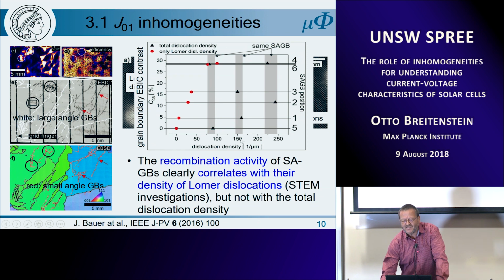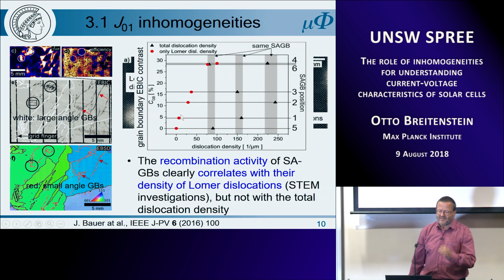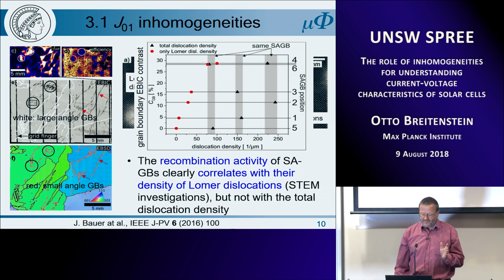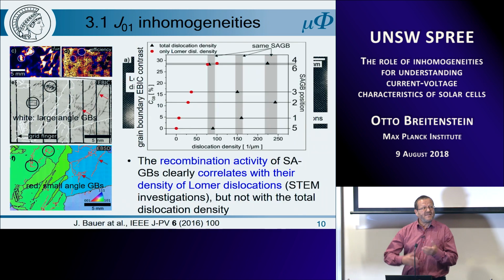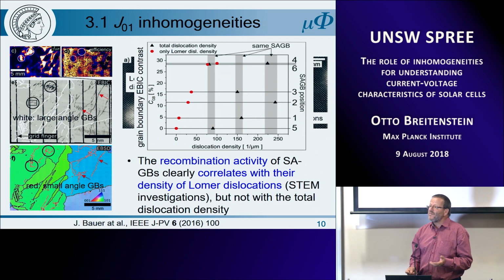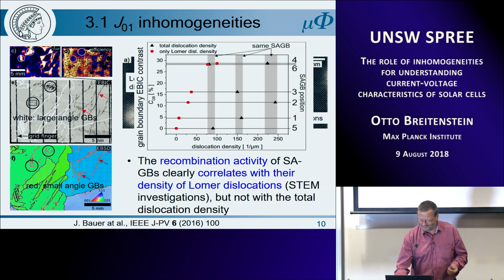total dislocation density. And you see the total dislocation density does not correlate with the contrast, but the Lomer dislocation density does. So we believe that the recombination activity of these grain boundaries clearly correlates with the density of Lomer dislocations, but not with the total dislocation density. And therefore we think that we have identified the major recombination cause. I mean, this does not answer the question how to avoid this. This would be the next thing.